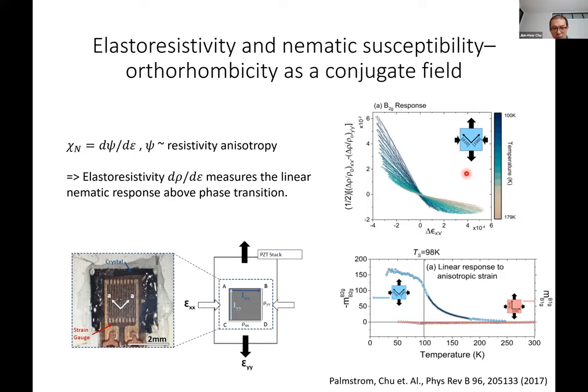Now, I don't have a full answer for this, but my interpretation is that this is evidence that the nematicity is deeply related to spin fluctuation, because when you either increase or decrease strain, then you're enhancing nematicity and increasing spin fluctuation, which increases the scattering and therefore increases resistivity.